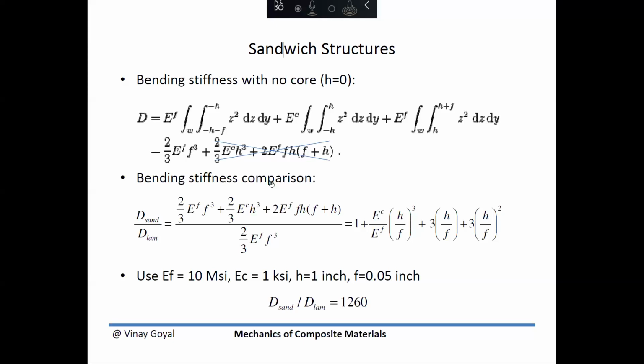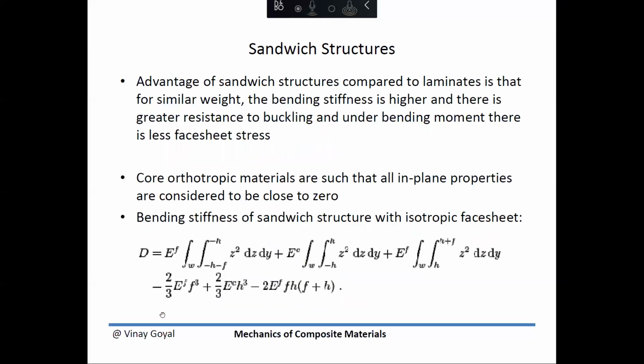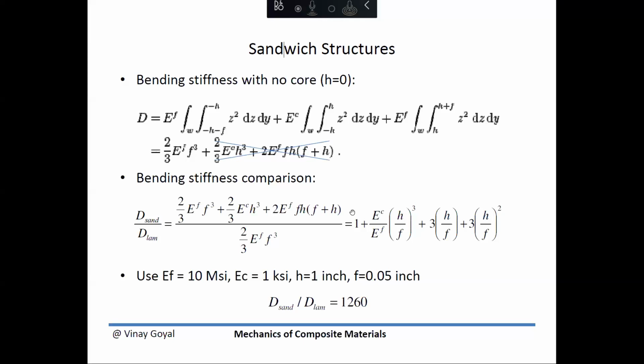If I compare the bending stiffness of the sandwich versus the laminate, for almost the same weight, I'll take this expression, which is for the whole sandwich, and divide it by this one for the plate with no core, and I work it through, this is what I get. And if I use representative values for a sandwich structure, so take the core is 1 inch, take the face sheet is 0.05 inch, take the core stiffness, which is 1000 PSI, and a face sheet similar to aluminum, I get that the bending stiffness for a sandwich is at least 1,000 times more than the laminate. So that shows the benefit of sandwich structures.